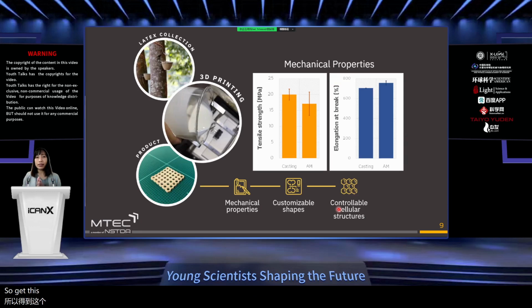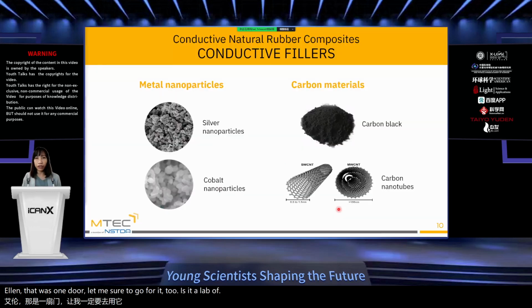So with this, a lot more doors are open for this technology. And there was one door that we chose to go for, which is to give it another function, which is to make it conductive. And in order to do so, we just need to mix conductive filler into the natural rubber latex before it is printed.